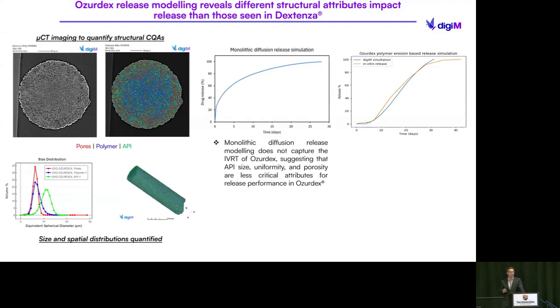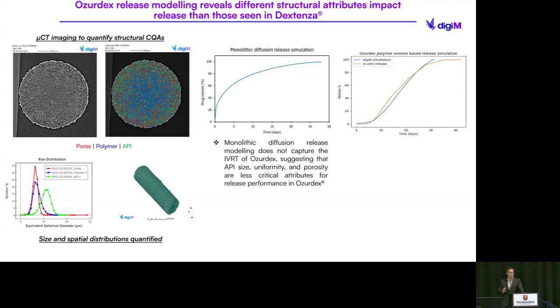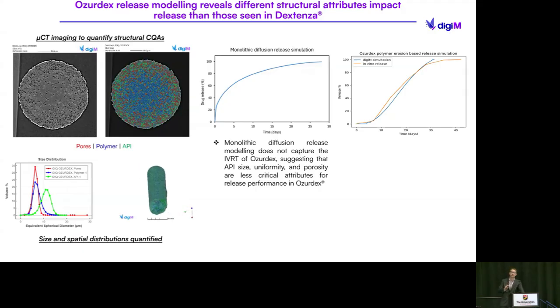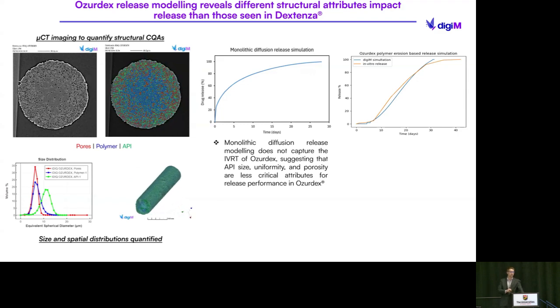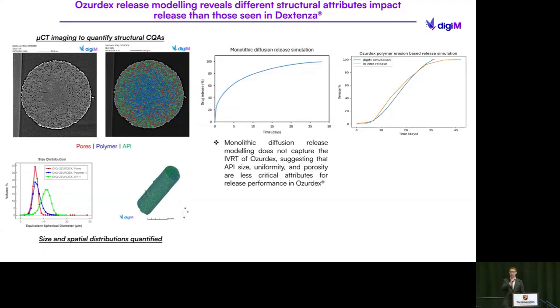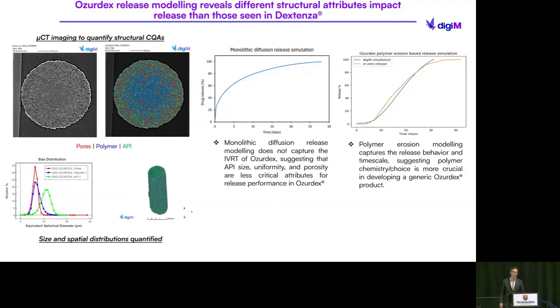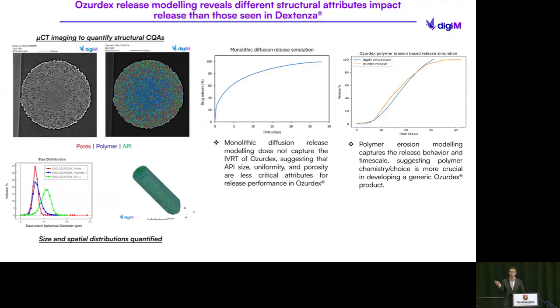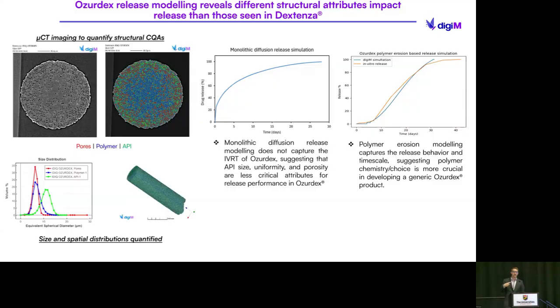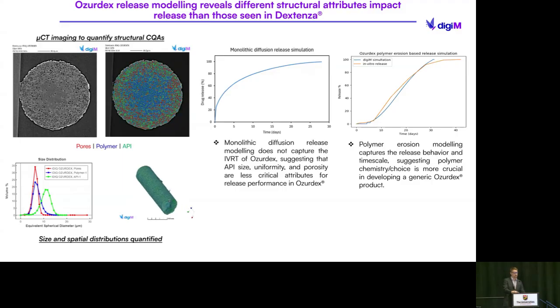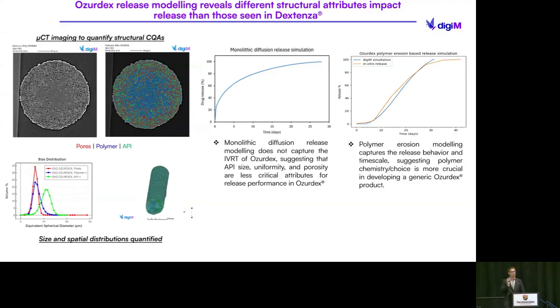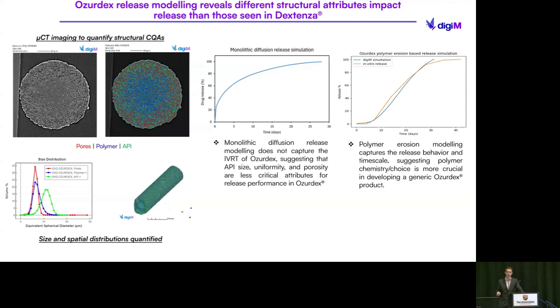So monolithic diffusion doesn't capture the in vitro release of Ozurdex, suggesting that the API size, the uniformity, and the porosity are less critical as quality attributes for the release performance of Ozurdex. And then we look to the other side. We did a polymer erosion-based method, where this time we don't even look at the API beyond knowing where it is spatially located relative to the polymer-rich domains. And in this case, we do an excellent job of actually capturing those same features, which suggests that in the case of Ozurdex, when you undergo release, the more important dominating mechanism is going to be that erosion. And we learned this from the structure combined with some insight into how these are made.